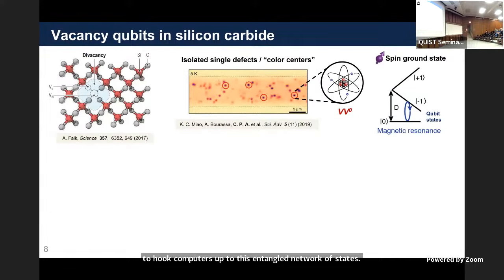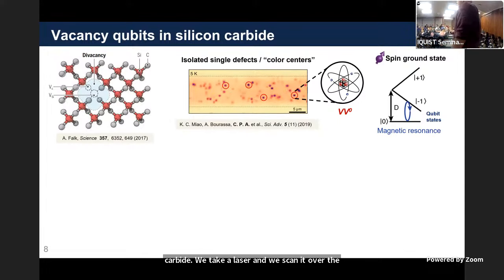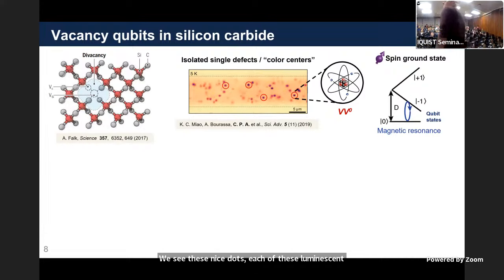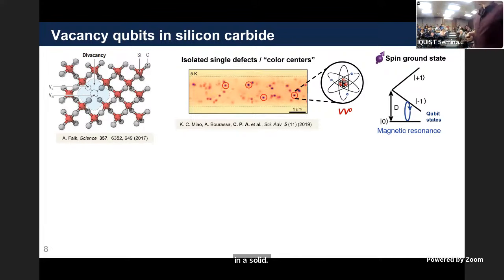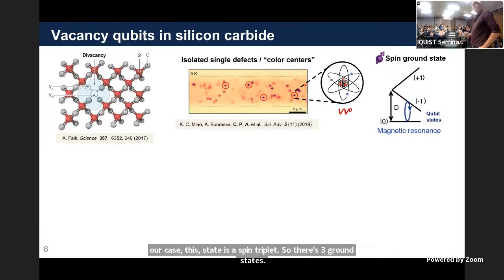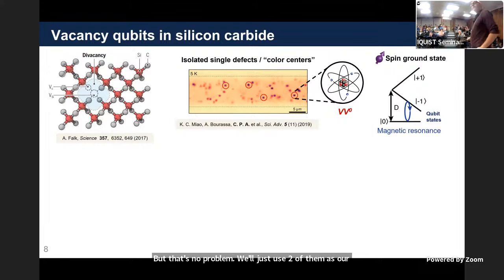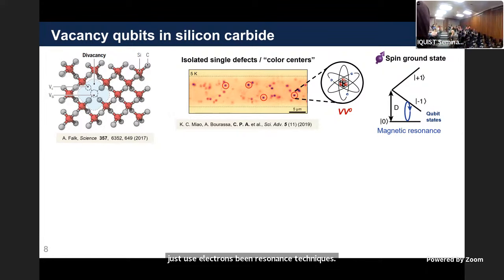So once again, we have this divacancy in silicon carbide. We take a laser and we scan it over the surface of our sample. We see these nice dots. Each of these luminescent dots is a single defect, or this artificial trapped atom in a solid. In our case, this state is a spin triplet. So there are three ground states, but that's no problem. We'll just use two of them as our qubit. And because it's a simple electron spin, we can just use electron spin resonance techniques to drive, tune, and manipulate this state using AC microwave magnetic fields and DC magnetic fields.